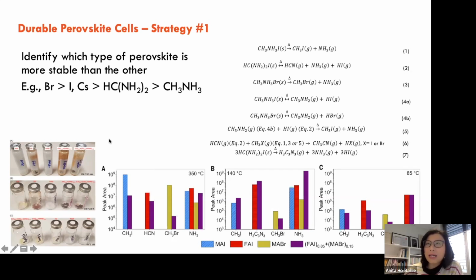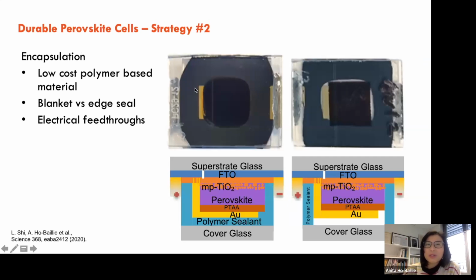And in terms of the cation, the component in the A site, the inorganic version, cesium, is a lot more stable than the organic ones, formamidinium and also methylammonium. We also found that if you mix the precursors together, you will have unwanted things happening. For example, you can see that these two reactions are reversible, but as soon as you mix some of the organic components together, it drives the reaction forward, and therefore the decomposition reaction keeps going. So this gives us a lot of insight in terms of how we want to mix and match the perovskite components. After we found out what's happening and what drives the reaction, we use packaging methods to protect them.